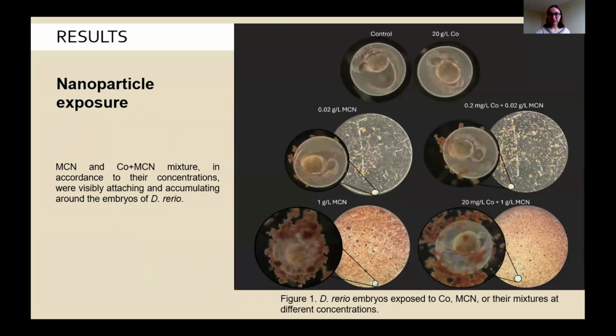And so from the very beginning, we could already observe the attachment and accumulation of magnetic chitosan nanoparticles around the embryos of Danio rerio. Here on the top left of the figure, you can see the control group, an embryo that is not affected by nanoparticles. In the middle, you can see lower concentrations of MCN and MCN together with cobalt. And on the bottom, you can see higher concentrations.